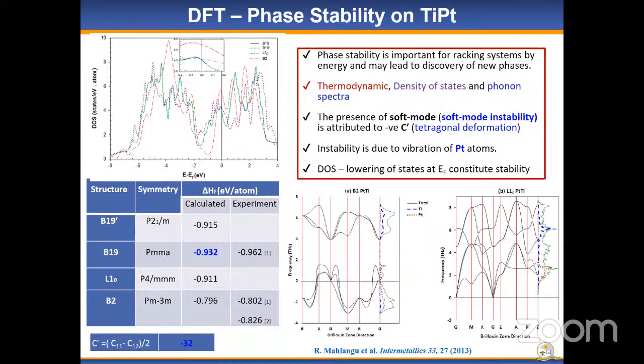So it is possible that you can find new phases when you probe into the negative or imaginary modes of the system. At each and every mode, you can come up with another new structure and then check what that structure means. In some cases, you might find a structure that can be stable, which was never predicted. Like in this case, the L10 structure was never shown in the first diagram. And then in this study, we were able to make that prediction and make a suggestion for this structure to be incorporated into the phase diagrams. And this was a success story for these calculations.